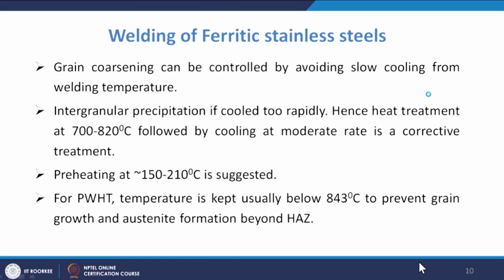So grain coarsening can be controlled by avoiding slow cooling from the welding temperature. Intergranular precipitation occurs if cooled too rapidly, hence heat treatment at 700 to 820 degrees followed by cooling at a moderate rate is a corrective treatment. Preheat treatment at 150 to 210 degrees is suggested, and post-weld treatment temperatures are usually kept at 843 degrees centigrade to prevent grain growth and austenite formation beyond the HAZ. Okay.